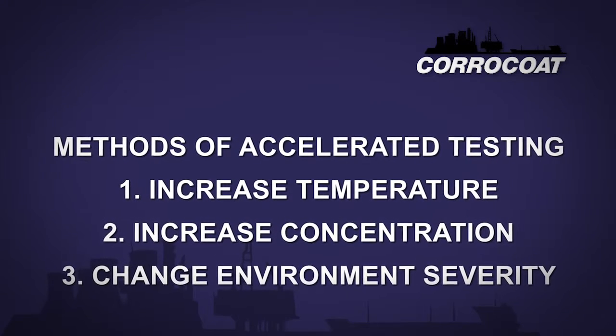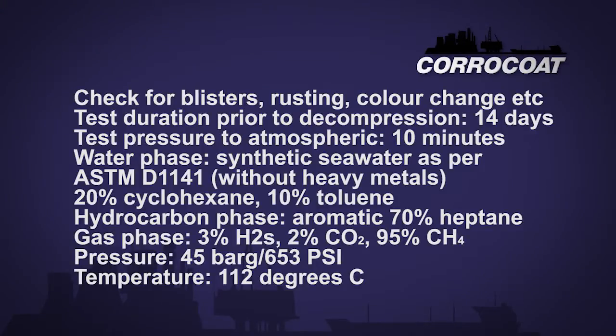What is changing the test environment? Changing the test environment is surprisingly common for testing within the oil industry, often due to the difficulty in obtaining and shipping even small samples of crude oil. For best results it is always good practice to test the actual oil in question. The client insisted on testing using a blend of hydrocarbons including a low molecular weight aromatic substituted for the oil. The coating was tested in an autoclave for explosive decompression and failed. Whilst it was true that a fraction of a percent of the low molecular weight aromatic would have been present within the oil, this test environment bore little resemblance to that of the process for which the coating was selected.